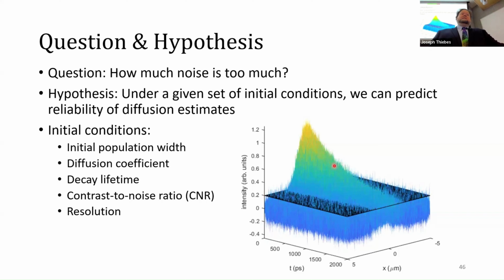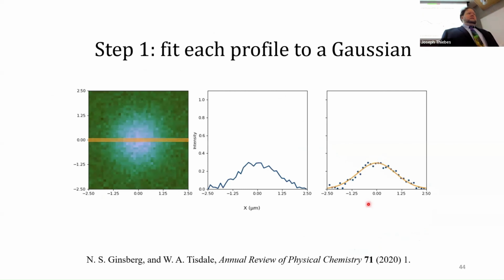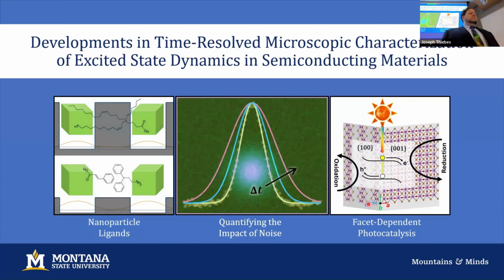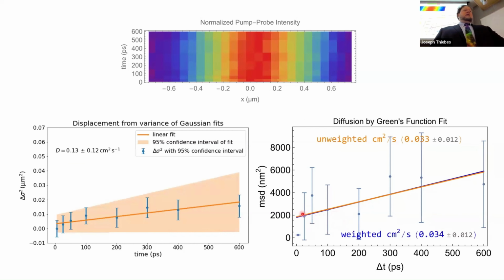So I started asking, at what point do these measurements start to become questionable? If you were to normalize these peaks, the noise would get more and more intense, because the noise becomes more prominent and more impactful as time goes on in this measurement. That was a big part of my question. If you look at these, the error bars represent the uncertainty of each individual time frame. And then we have a plus or minus value here, which is related to the slope of this fitted line. Those are two separate uncertainties that I don't think really capture the fullness of the uncertainty.